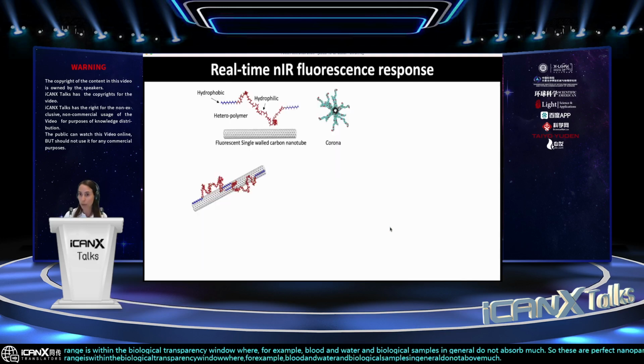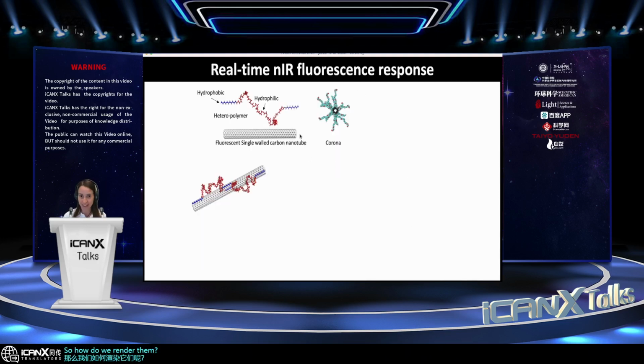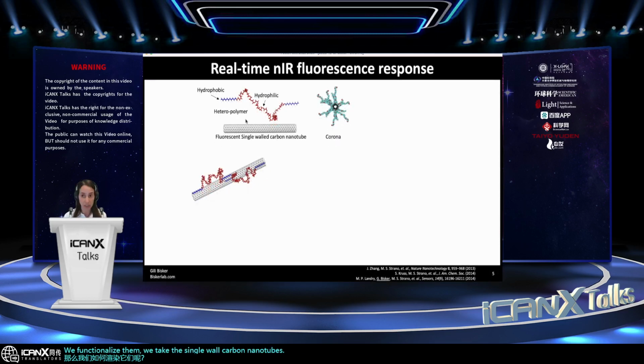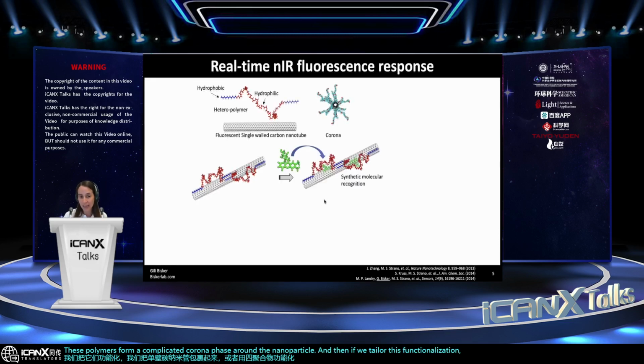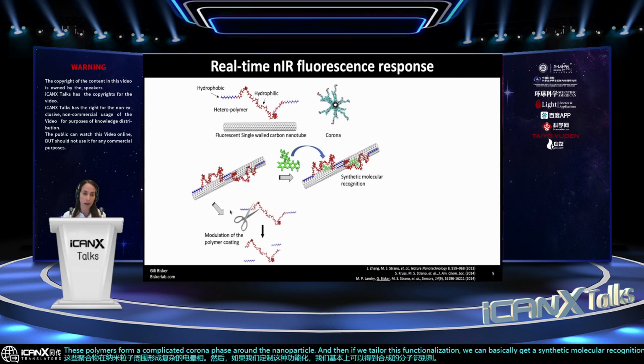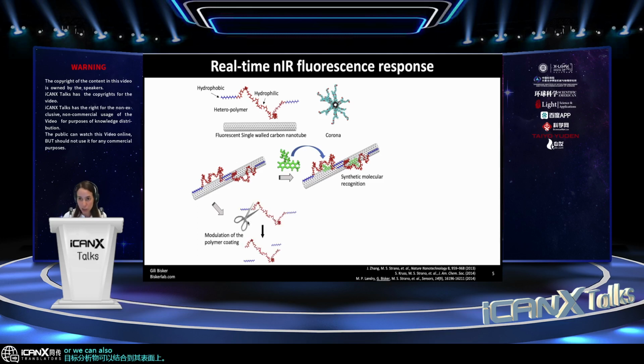So how do we render them sensors? We functionalize them. We take the single-wall carbon nanotubes, we wrap them or functionalize them with hetero-polymers, which have hydrophobic and hydrophilic parts. These polymers form a complicated corona phase around the nanoparticle. And then if we tailor this functionalization, we can basically get a synthetic molecular recognition agent that target analytes can bind onto its surface. Or we can also induce changes or modulations to this polymer coating.